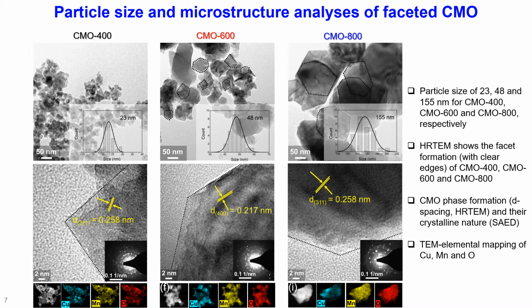Particle size and microstructure analysis of faceted CMO. Here we have shown TEM, HR-TEM and TEM elemental mapping of our CMO nanopolyhedra. Here the particle sizes of CMO 400, CMO 600 and CMO 800 are 23, 48 and 155 nanometers respectively. It confirmed that the particle size of CMO has increased with the increase of annealing temperature, and the clear faceted morphology has been confirmed via HR-TEM images of all the CMO nanopolyhedra.